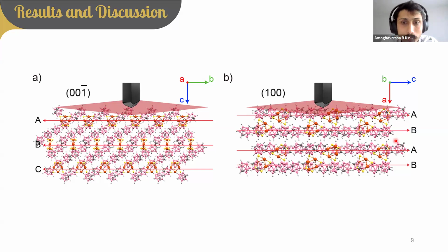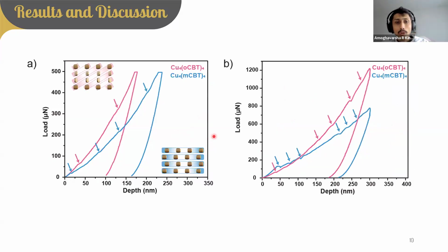When we do the indentation, we just press into the sample and take out the tip. Two different techniques can be used. One is load controlled indentation on the left side and the other is displacement controlled indentation on the right side. In the first one, load controlled, we specify the load and measure the change in displacement. And in displacement controlled, it is just vice versa.